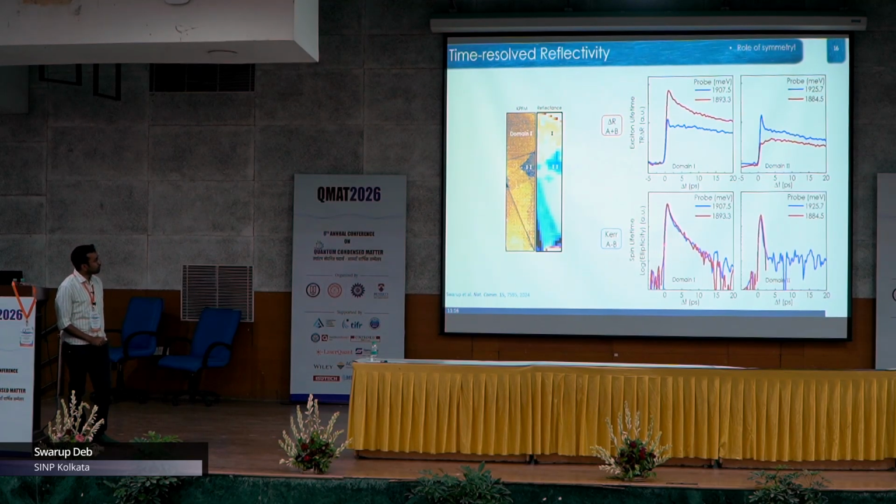On the other hand, when I look into the spin signal, the spin lifetime of the excitons, in one domain the lifetime is about 15 to 20 picoseconds. However, in the other, this vanishes as early as it gets. It is very close to the temporal resolution that we have. So after 2 years after this publication, we still don't know why this happens. Maybe we need some more theory about it, but maybe it is the out of plane ferroelectric field that is generating some sort of SOC, but we're not very sure of that.